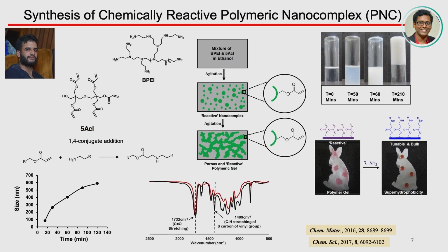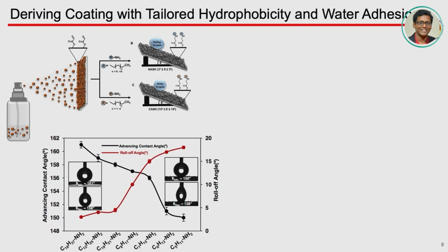Now, our aim was to deposit this nanocomplex at a different time frame, pre-mature those reactive nanocomplexes, so that they do some sort of cross-linking gelation at the surface and form a porous polymeric coating. And that's exactly what we got. Depending on the solvent system and additives, we can accelerate this sol-gel process, and we got this reactive porous coating. Now you go for different chemical modification, again using this 1,4-conjugate addition reaction with different kinds of alkylamine, and you can achieve non-adhesive superhydrophobicity as well as adhesive superhydrophobicity.